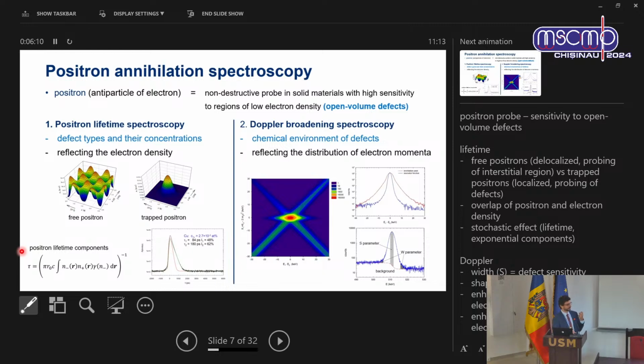And in order to get the full information about the defect structure inside, you can use the complementary method, which is called the Doppler broadening spectroscopy. Unlike the lifetime spectroscopy, which is sensitive to densities in the real space, the Doppler broadening spectroscopy is sensitive to the distribution of electron momenta in reciprocal space, and therefore it's sensitive to the chemical environment of the defect. So together you can effectively describe the defect structure of your materials.